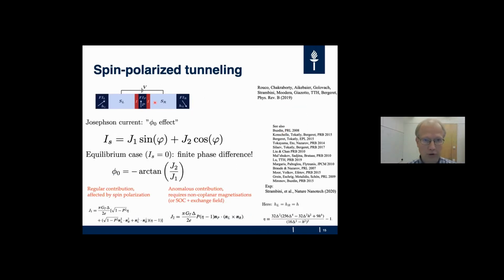Okay, if you have two superconductors, you can sort of extend this tunneling description from quasi-particles to the Josephson effect. One interesting thing that you get from there is the so-called phi-zero effect in the general case described here, so that the supercurrent contains not only the sine phi part, but actually also the cosine phi part. This means that in the equilibrium case where the supercurrent is zero, or when you don't connect this to any external circuit, then actually the equilibrium phase difference is finite.